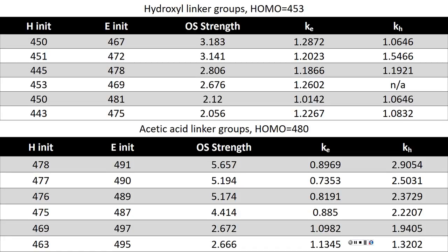His question is why it is different in the two different systems, in the presence of acetic acid and hydroxyl link. This is clear because the difference in these passivating molecules really plays a role, right? You have different pathways for the electrons and the holes to follow, essentially. So these aren't going to be the same because it's a physically different route. One can analyze deeper and see if there are different styles of hybridization between the donor and acceptor, and it will affect it for sure. But you probably will talk about it later. This is a very preliminary slide, and it is not his last talk.